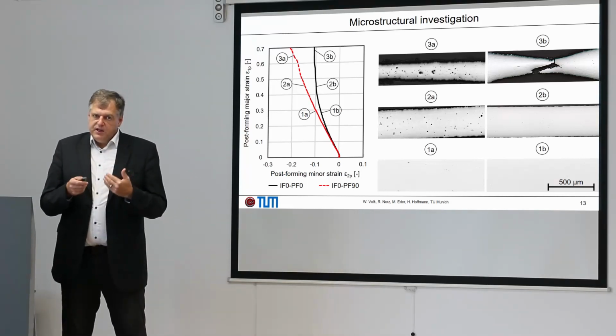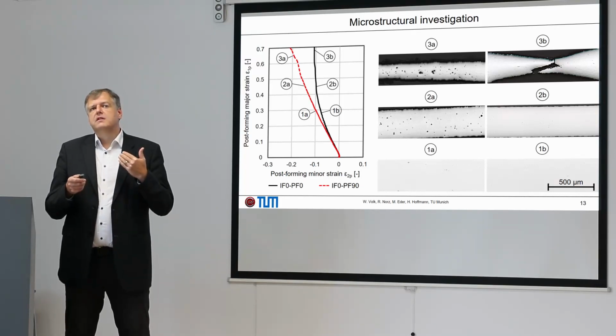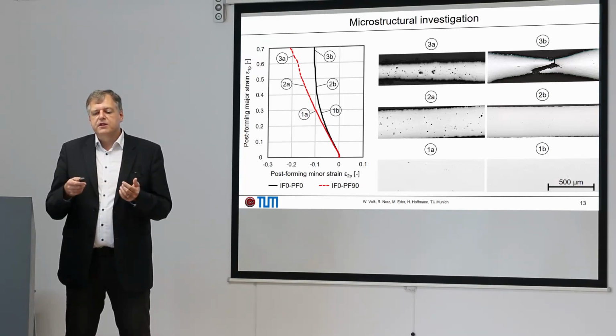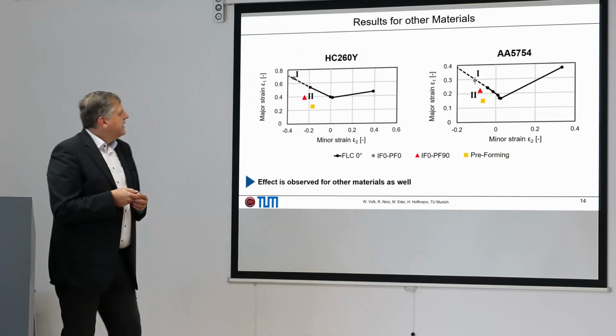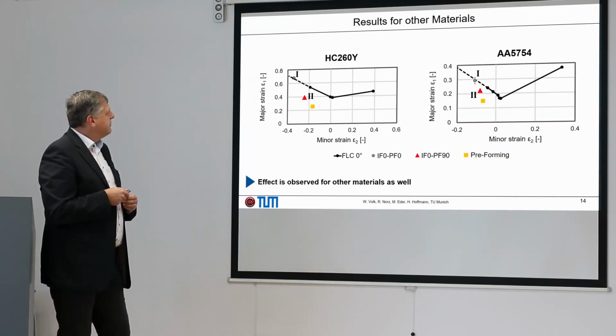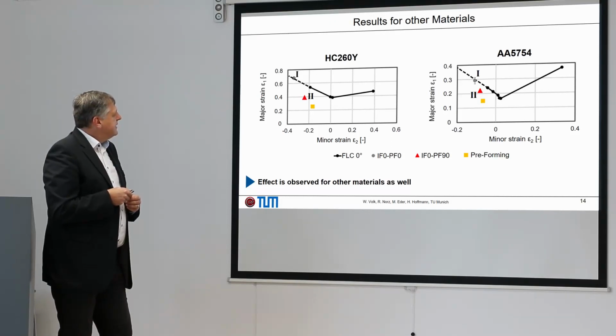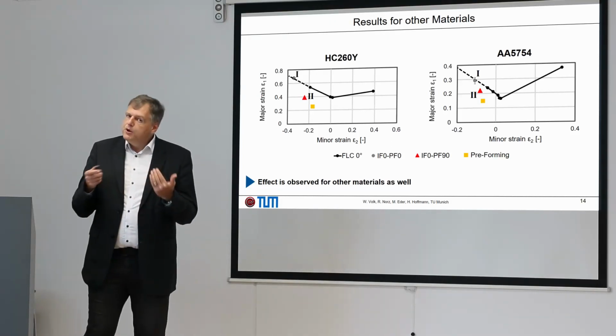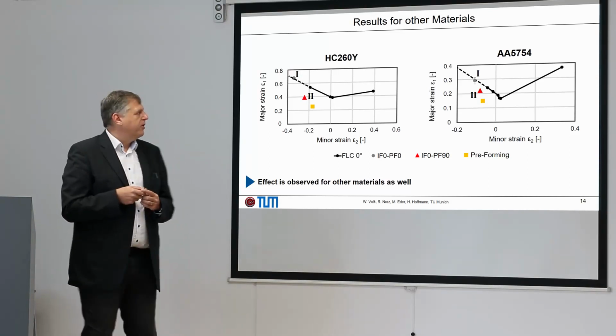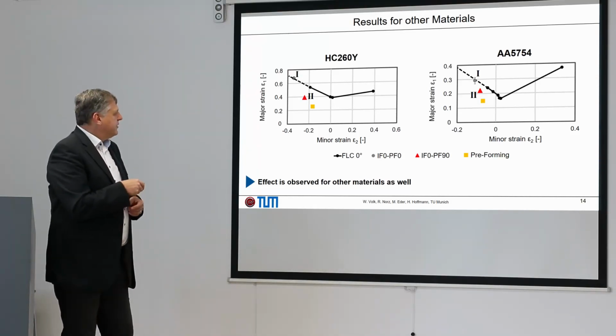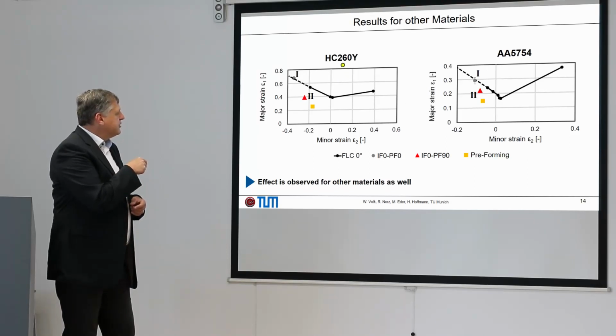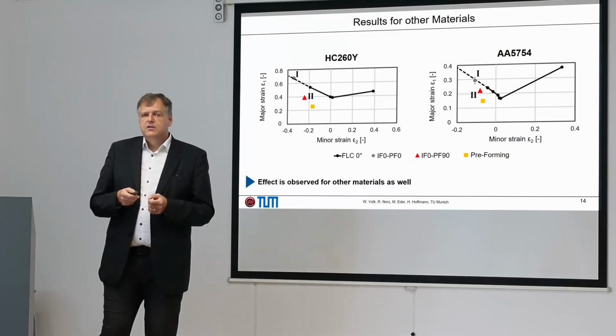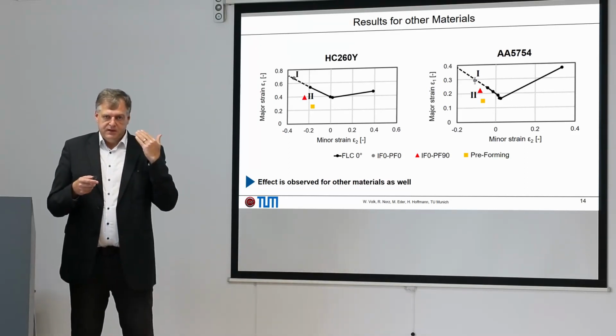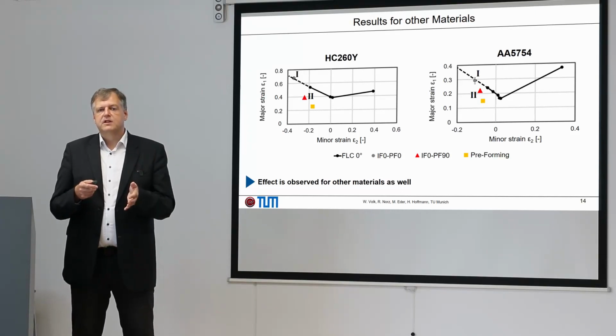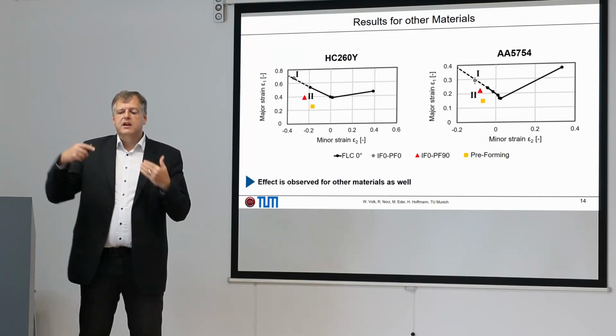To see if it's really a physical effect which can occur also for other materials, we used other materials. And here, for example, the IF steel 260, which is one of the purest materials we are using in sheet metal forming, or also for aluminum. And what you can see here, also for this interstitial free material or the aluminum, this effect occurs. So let's see, even after this large pre-strain, for different materials, this shear failure can occur.